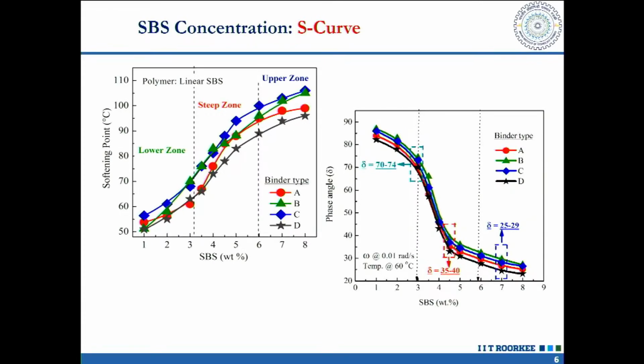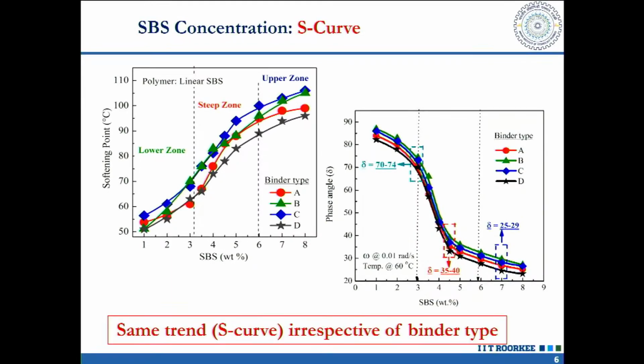We can see from the graph that when the percentage of SBS increases in the bitumen, the phase angle decreases considerably. A higher phase angle indicates lower elasticity, and when we keep adding polymer to bitumen, the elasticity increases considerably, which is reflected in the lower value of phase angle.